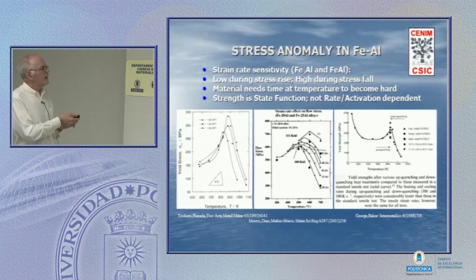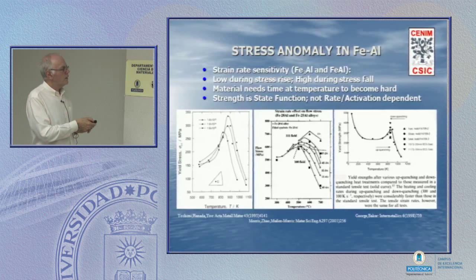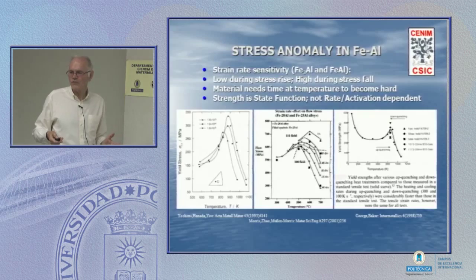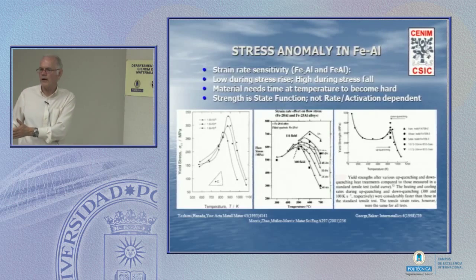So what we have is the anomalous strengthening, which is very strange, that's why it's called anomalous. We have here a material which, if I test it at room temperature, will have a strength of 100, 150 megapascals. If I test it at 600 Celsius, it has a strength of 300 megapascals. It's a wonderfully strange thing, a material that is much stronger at high temperature than at low temperature.